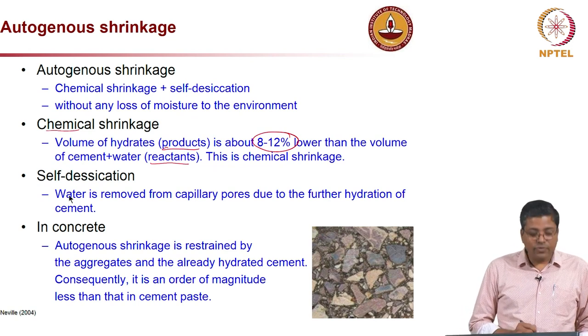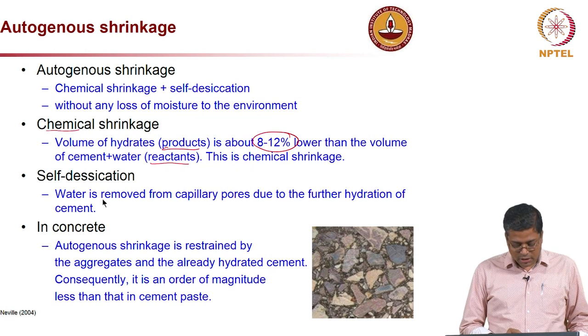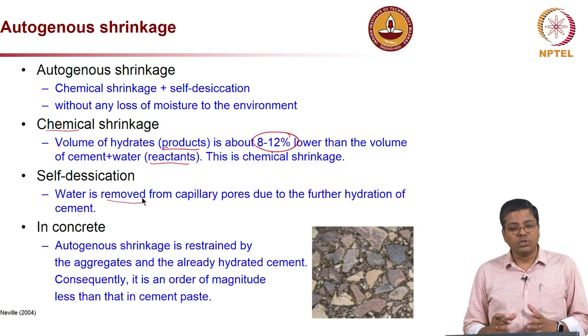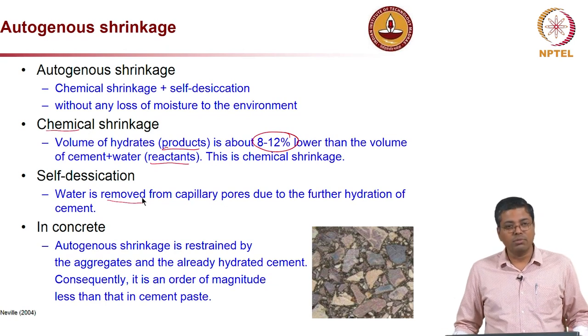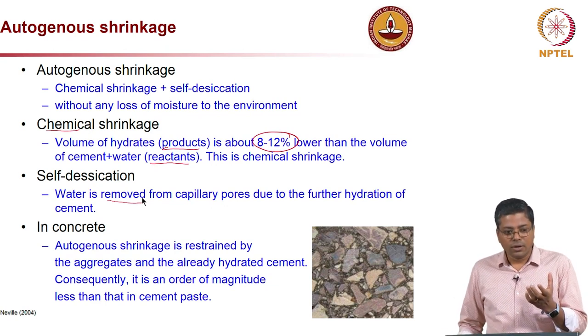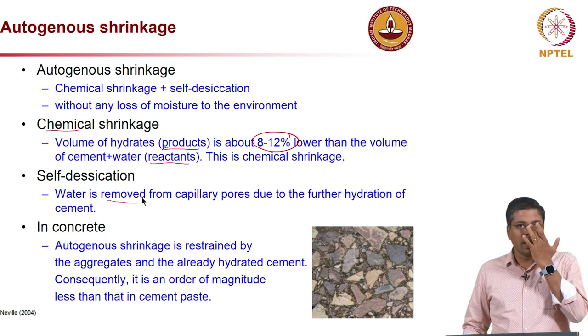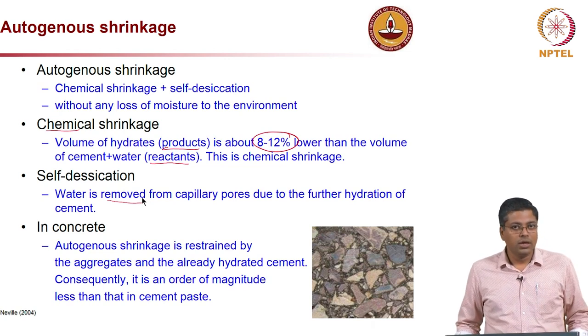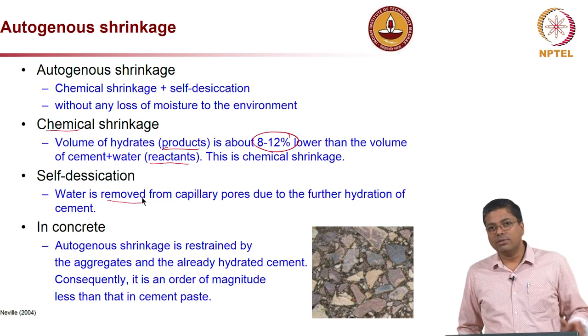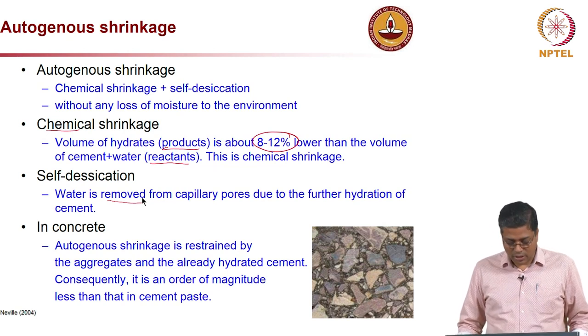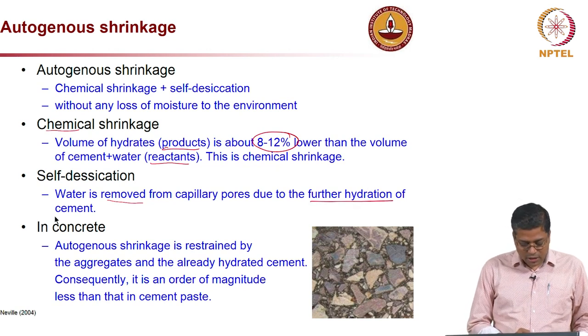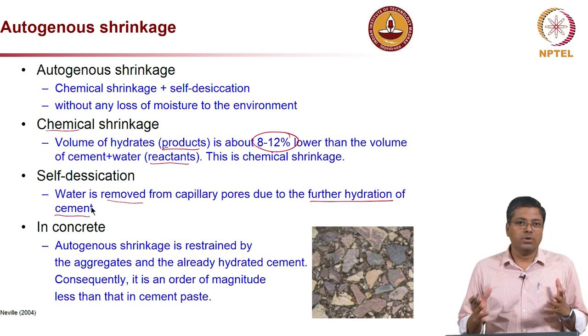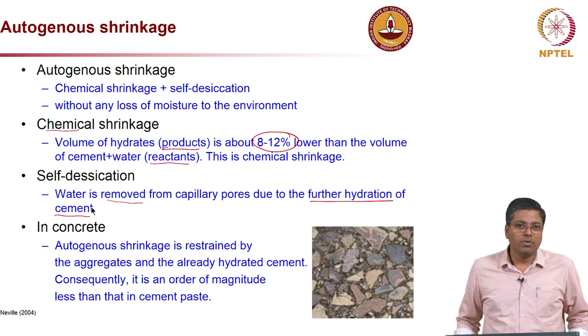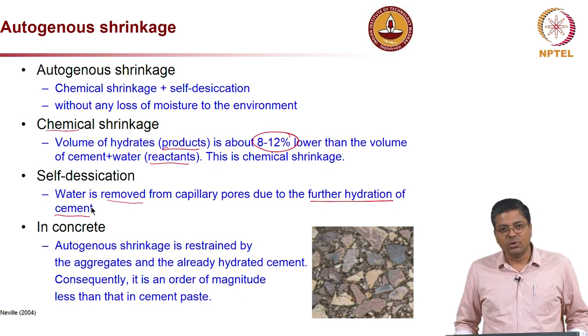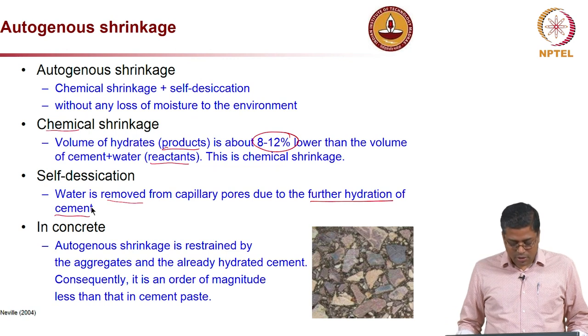And self desiccation is mainly when water is removed from the capillary pores, but not to outside the concrete system. Especially this kind of mechanism happens in low water cement ratio concrete, where you will still have some unhydrated cement left in the concrete. So that is why here we are saying further hydration of cement, or enough, you do not have sufficient water available for the full hydration of the cement system. So as and when it is available, it will use.